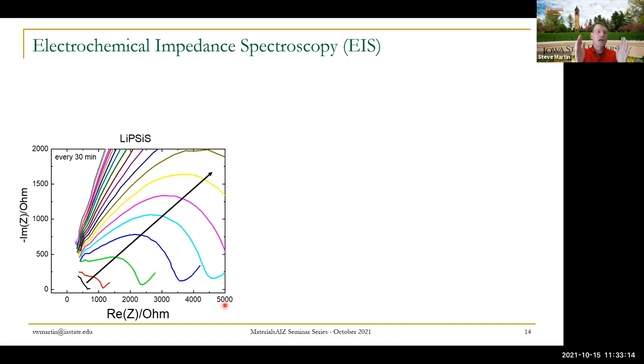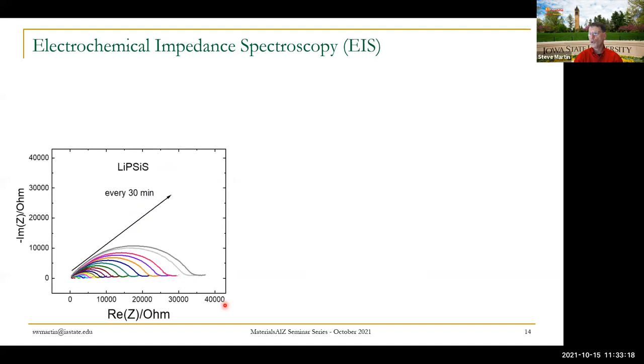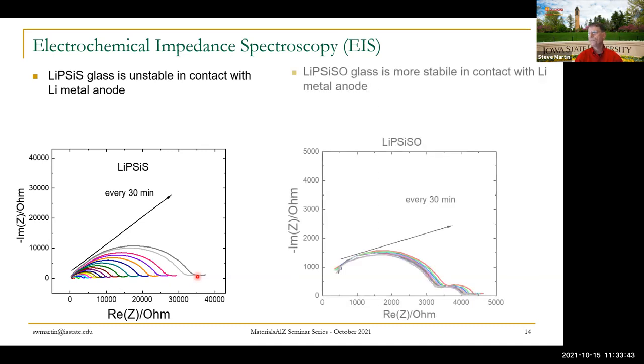It would basically just shut down the battery. You wouldn't be able to get any current through it. This is just to show you what that looks like. It started there. If you look very, very carefully, you can see that tiny little arc down there. Because the conductivity of these glasses is very high, the impedance is low, but you can see it grows. This is out to about 30 or 40,000 ohms. So this is a non-starter for a battery. And so the lithium pure sulfide glass reacts quickly and is unstable in a lithium metal anode.